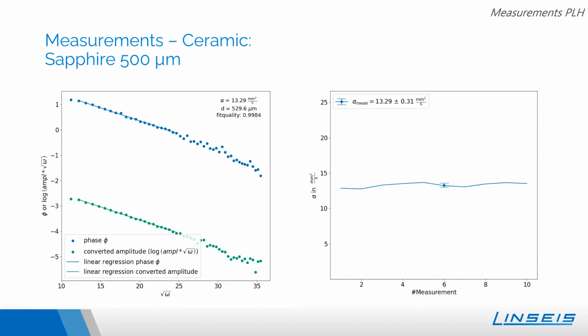Our next example belongs to the category of ceramic materials. It's a sapphire, a well-known material, and in our case, approximately 500 micrometers thick. And its thermal diffusivity should be around 13.3 millimeters square per second. And what we expect is what we get. The measurement curves are good, the fit is great, and the evaluated thermal diffusivity is nearly exactly the value we should measure. Again, the repetition of the measurement is quite good, which is displayed on the right side. So you see, it's still the value you expect.